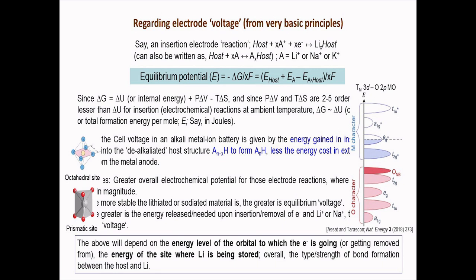But all of these depend on where the electron that is coming in from the external circuit and the lithium ion that is coming into the structure are getting stored. For example, if the lithium ion is getting stored in the octahedral site, it will lead to one equilibrium voltage. If it is getting stored in another type of site, say prismatic, lithium does not get stored in a prismatic, sodium does, but suppose tetrahedral, it will lead to another cell voltage, even if the electron is coming to the same energy level. And if the lithium is going into just one type of site and the electron changes the energy level to which it goes, that will also change the equilibrium voltage, because it will change the overall energy of the reaction.